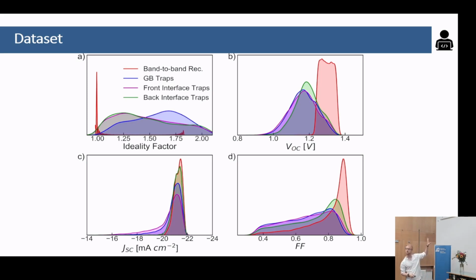And those are only the one-sun values, but we also used the light intensity dependent ones. However, in the light intensity dependent one, you also have to limit yourself a little, because if you go too low in light intensity, then those values are dominated by other effects like shunt resistance, for example. And if you go too high, then you're limited by series resistance. So you really take a few values next to one sun.